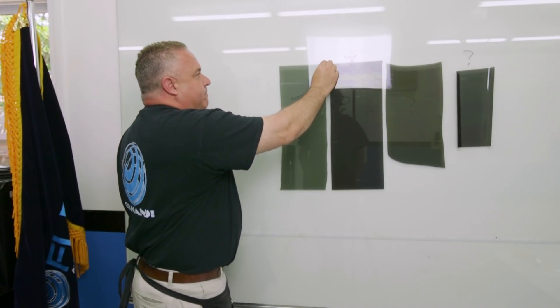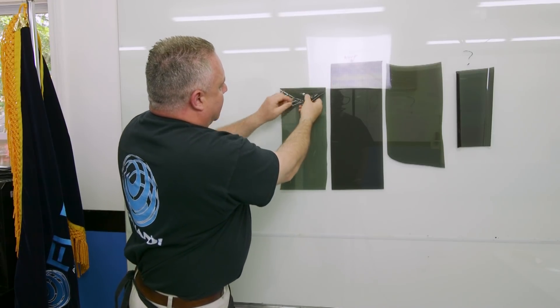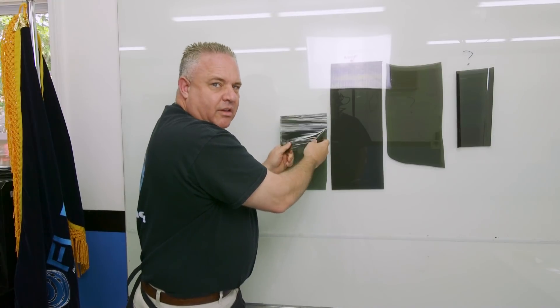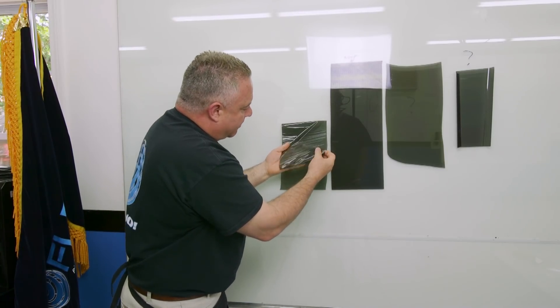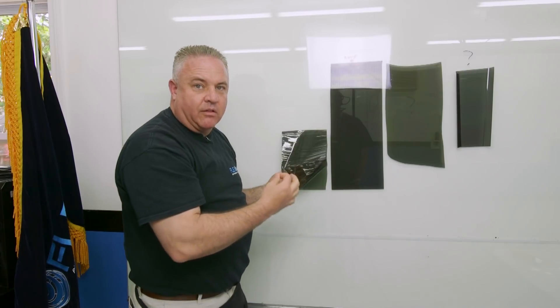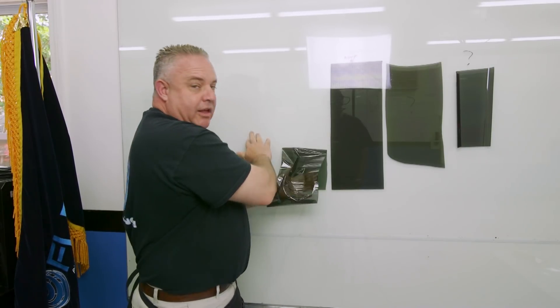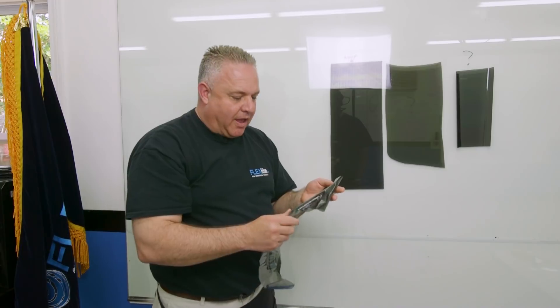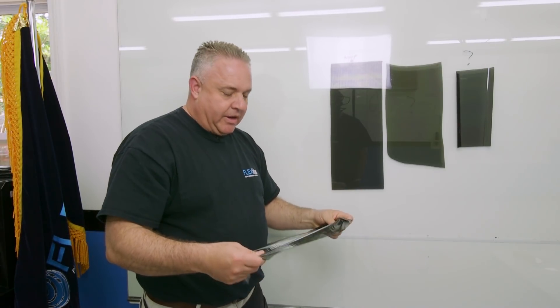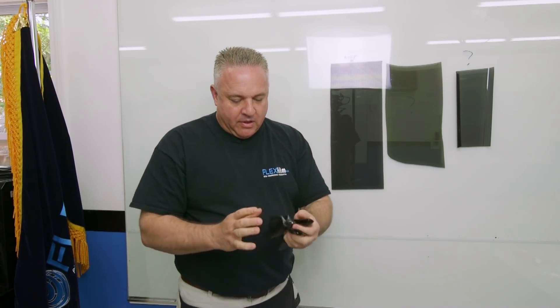This is LLumar ATR. It takes a little more to pull it off, and it does the same thing — all the glue is remaining on the glass, with hardly any patches on the film. Very aggressive, thin glue. It sets up really fast — I bet it took maybe only 10 minutes to set up, similar to the Global. Just because it wasn't hard to pull this off the glass doesn't mean this adhesive is in any way unsuccessful. It's just different. There's not enough glue left on the film to do a fair fold test. That's the Lumar film.